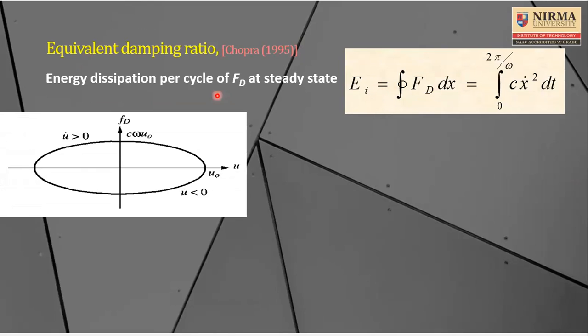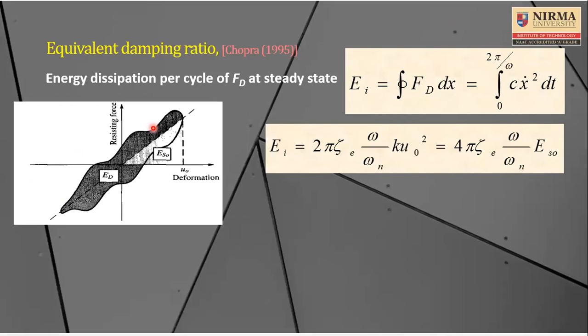So as you are aware, if you subject any structural element to sinusoidal loading, and you calculate the total energy lost in one cycle by doing the integration and calculating the area of this load versus deformation plot, and then you equate that with any other hysteresis loop available for your material, like masonry infill, like a red clay brick or an AAC block or a fly ash or any other kind of material.